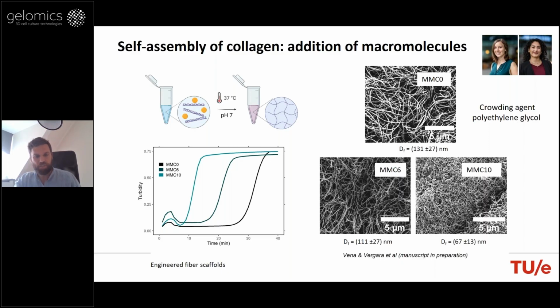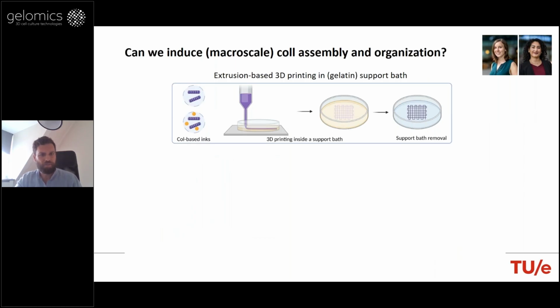And then we confirmed this with scanning electron microscopy analysis, showing the images here on the left side, where you see that at higher concentrations of PEG, the crowding agent, it led to a highly dense network of collagen with a high density of thinner fibers of collagen. So typically the crowding agent plays a huge role, and we can somehow mimic or approximate the conditions in which this happens in living tissues.